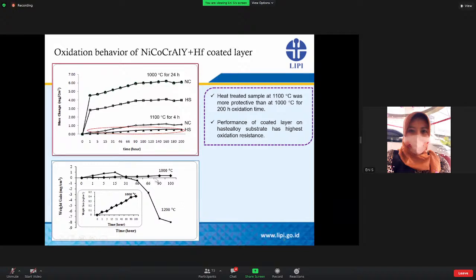The oxide growth occurs by the diffusion of oxygen to the coated layer at the initial growth rate of the coated samples, followed by a steady state of the alumina oxide scales. The weight gain reached 0.4, as you can see in this inset figure, after 100 hours.